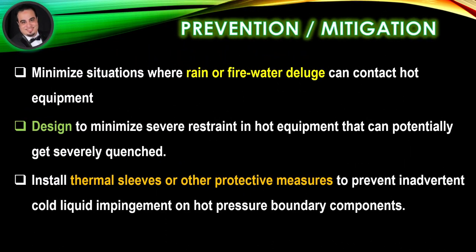Prevention and mitigation: minimize situations where rain or fire water deluge can contact hot equipment. Design to minimize severe restraint in hot equipment that can potentially get severely quenched. Install thermal sleeves or other protective measures to prevent inadvertent cold liquid impingement on hot pressure boundary components.